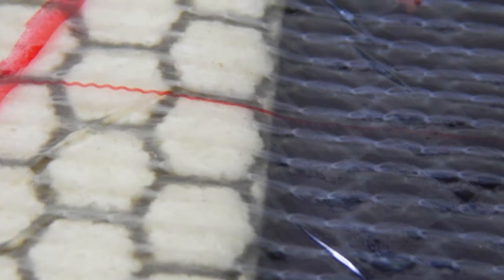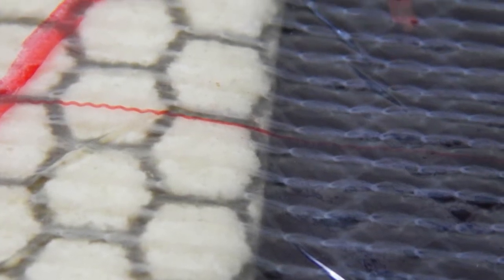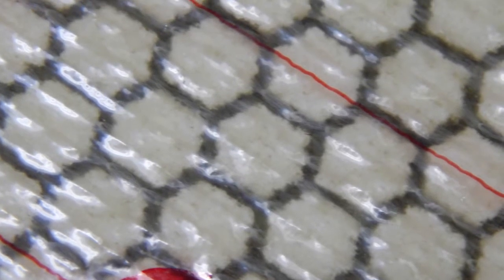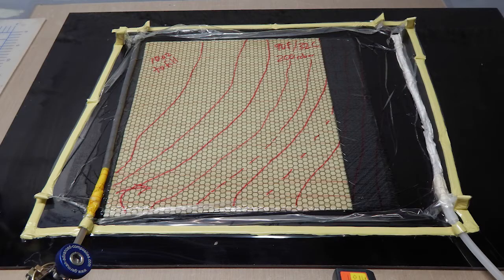But the laminate itself looks nice and tight. There's no air. No leaks. And in between the cells and the Soric you can see it's very tight. And again they're looking at the lines from this perspective. You can see how uneven the fill was.